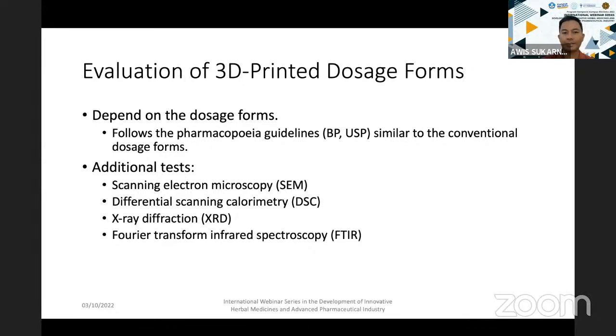The first one is the scanning electron microscopy, or the SEM. Sometimes when you print the sample and look at it, it looks very smooth. But when you look closely at the surface, you can see it isn't that smooth. Maybe it's rough, or maybe it's a porous sample. So that's why it's good for you to have a SEM image of the sample, so you can really study the sample.